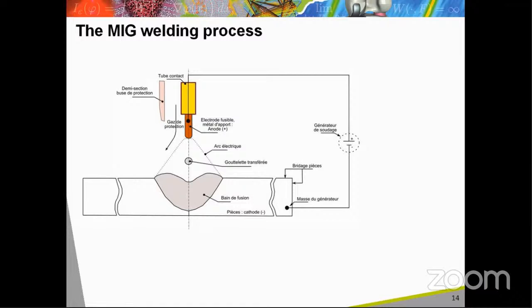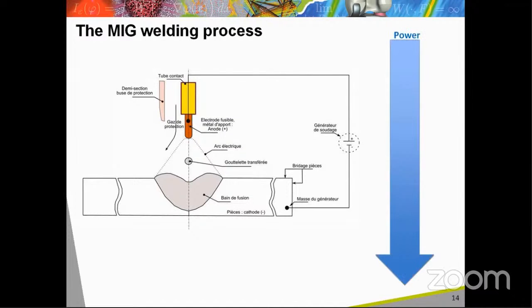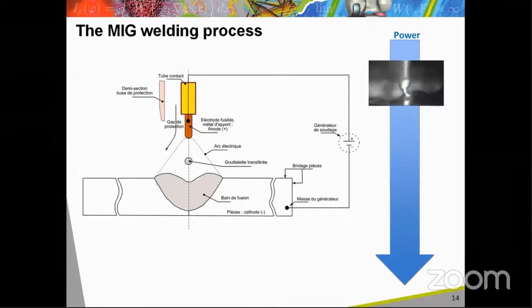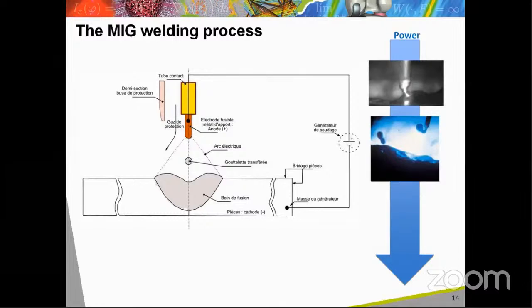According to the wire diameter and the arc power, various melting modes corresponding to different metal transfer regimes can be observed. When the arc power is low, the wire tip melts slowly and the wire, which is continuously fed, enters regularly in contact with the melt pool formed at the surface of the welded samples, creating a short circuit and the arc extinction. This transfer regime is called short circuit mode and is a stable mode because the formed deposits are rather regular. When the arc power increases, the melting of the wire tip is faster and some large liquid droplets are sprayed, producing sputters and sometimes irregular deposits. This transfer regime is called the globular mode.